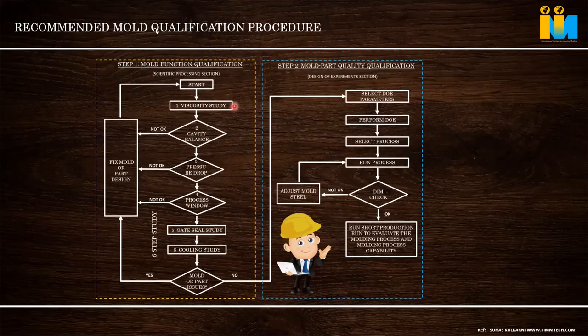Plastic raw material is non-Newtonian, so it wishes to be injected at a higher speed. If the injection speed is low or the injection time increases, then melt temperature drop happens. A 300-degree melt is injected into the mold. It flows very slowly, and it may drop from 300 to 200 and freeze off. That is not an ideal condition. So we say it has to be injected quickly without destroying the raw material property.